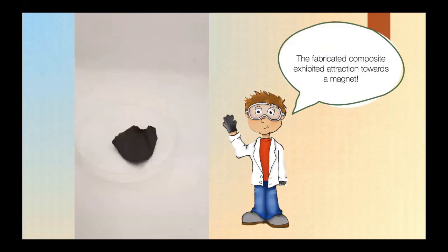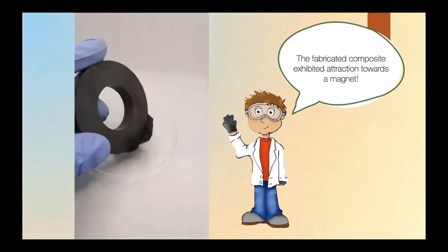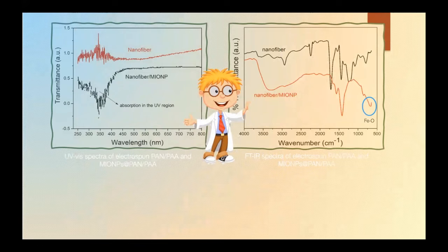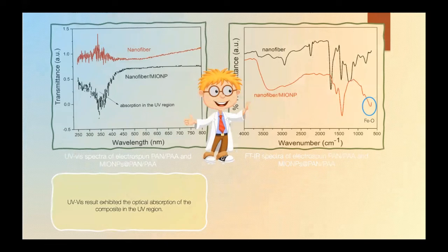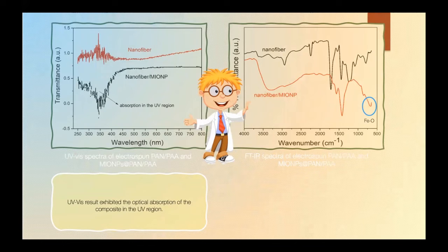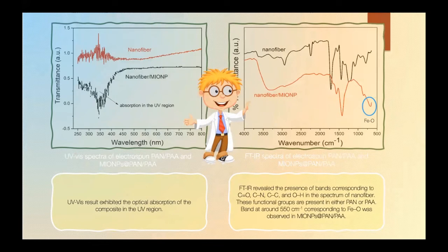Using an external magnet, we have shown that the produced composite is indeed magnetic. UV-Vis spectroscopy result exhibited an apparent reduction in the transmittance spectra of the composite in the UV region, suggesting that the sample has absorbed UV light as expected from metal oxides. Meanwhile, Fourier transform infrared spectral analysis revealed that the bands corresponding to the functional groups present in polyacrylonitrile and polyacrylic acid are present in the spectrum of the nanofiber. Moreover, a band at around 550 per centimeter corresponding to the Fe-O bond was observed in the spectrum of the composite, confirming the presence of iron oxide in the nanofibers.